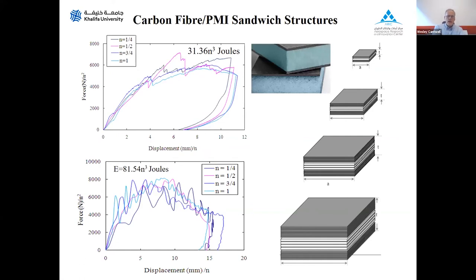So when we finished that, a number of years later, a PhD student at Liverpool, Zeewin, did some scaled impact work on sandwich structures, and they are shown here. These were carbon fiber PMI sandwich structures. Again, we scale the skin thickness. So you can see here, I've shown it schematically. You scale the core thickness as well. The way we did it here was to bond cores of the same thickness together, to increase the core thickness by bonding sheets together. But we managed to get four different size panels. These full size panels are in fact really quite large, quite expensive to produce.